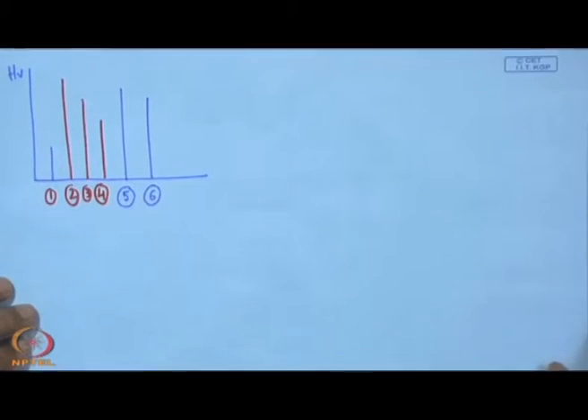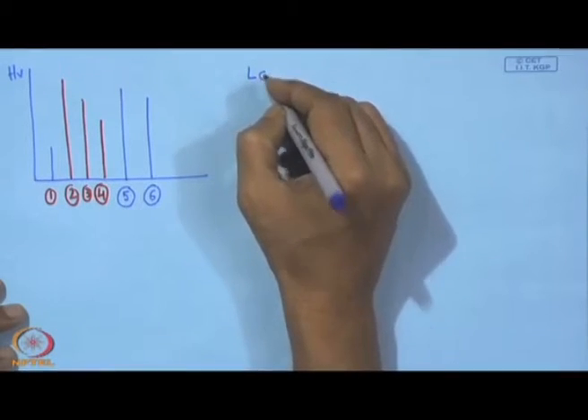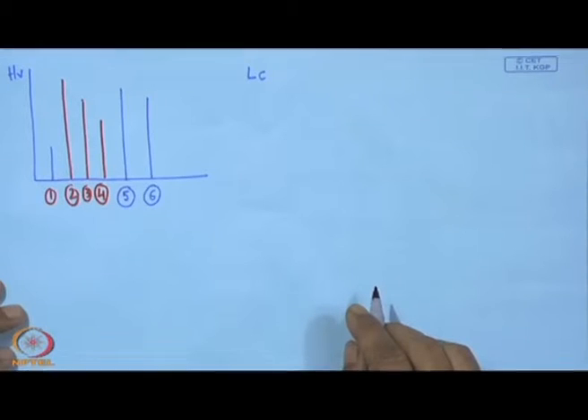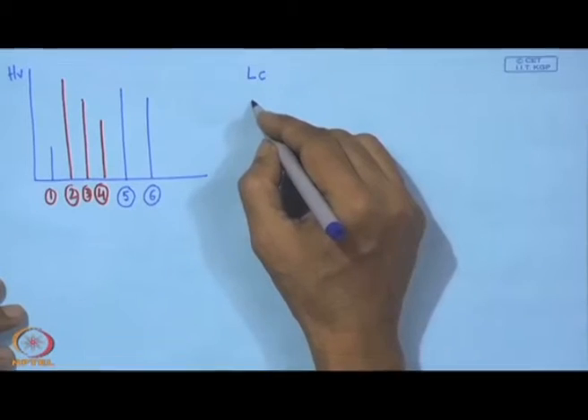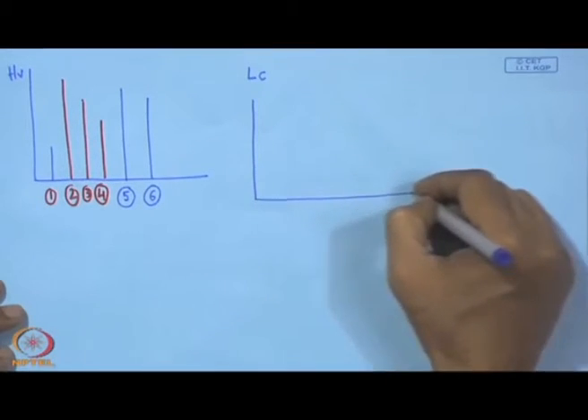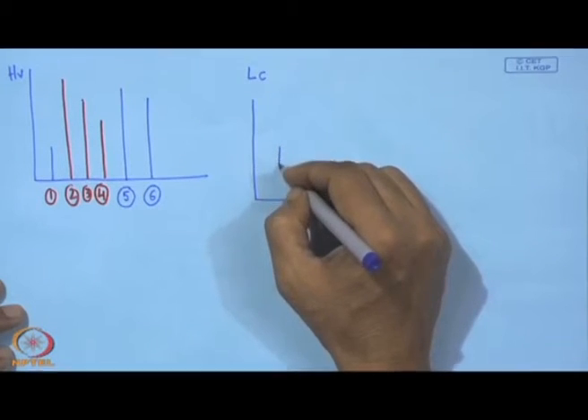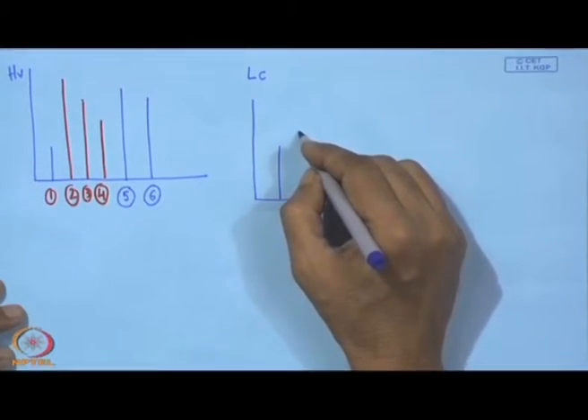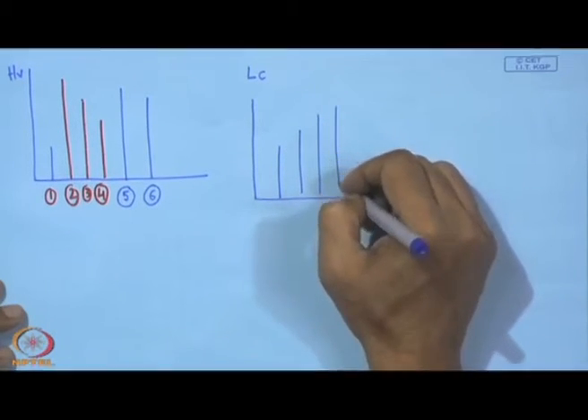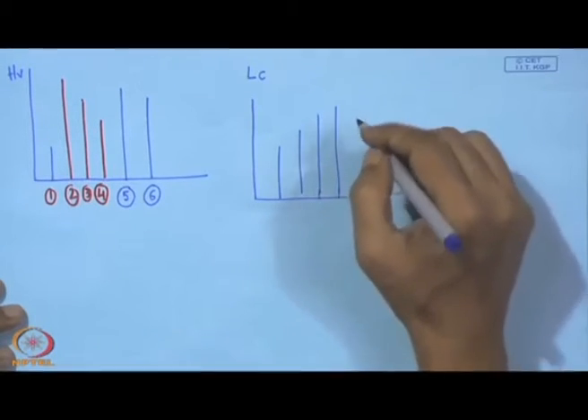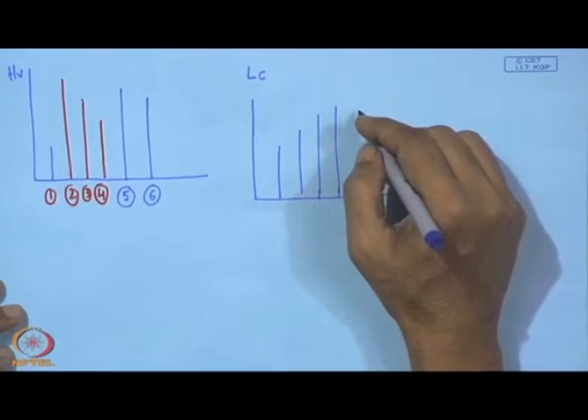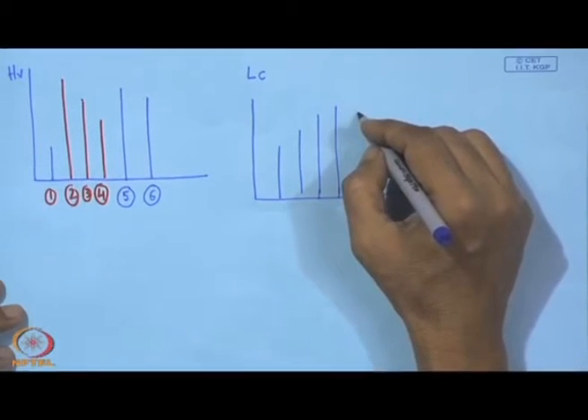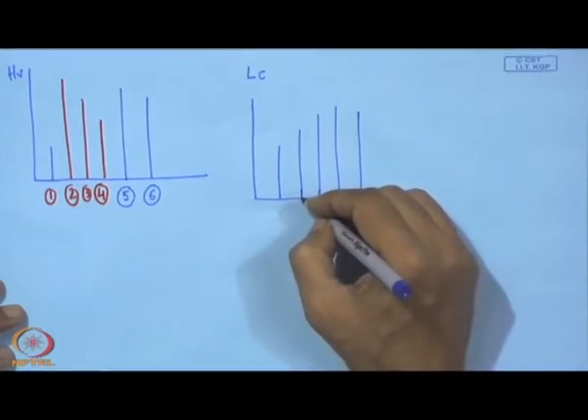So, this is one way we can find the hardness distribution, but one thing of immediate interest next will be what we call adhesion, that means the critical normal load which causes the first failure of the coating. On this scale, if we put the bar diagram, we can find that for all these 1, 2, 3, 4, and this is actually what we find here. So, this is something like that.